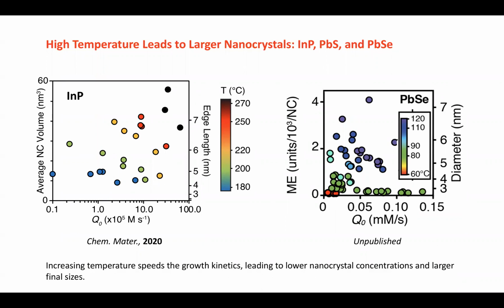Higher temperature, looking at the graph, the growth kinetics are going to go fast in the beginning, so there are fewer total particles, but then they get bigger. Exactly. If you keep the Sugimoto expression in mind, the number is inversely related to the growth rate. If the growth rate is faster, it takes fewer crystals to consume the solute. Those crystals can consume solutes very effectively in any kind of competition, and nucleation is less important. If the crystals stink at consuming solute, they go nucleate new ones.